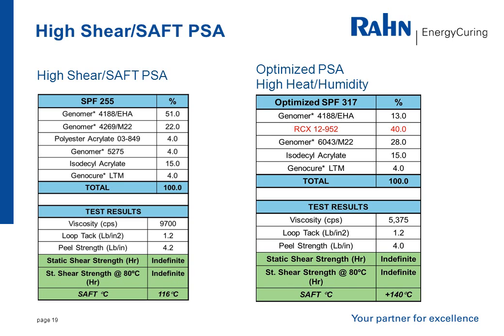Let's take a look at our standard high shear, high SAFT PSA formula versus the optimized high heat, high humidity PSA. By incorporating the experimental product RCX-12-952 at 40%, and a combination of Genomer 4188, we build in added heat resistance with our tackifying resin 6043 and diluent isodecyl acrylate. This optimized formulation allows us to maintain comparable loop tack, peel strength, and shear properties while giving an increase in our SAFT.